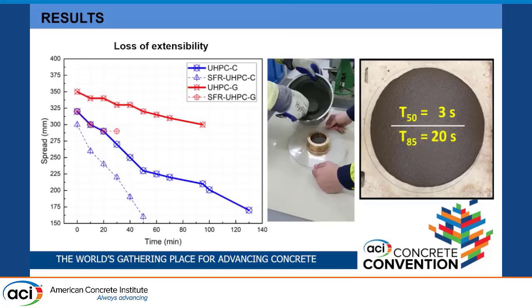Okay, and this is the graphic of the loss of the extensibility that is important for practical and industrial applications. And what we can see in the top, the red graphic is the one for the green concrete. So we can see that the blue ones that were made with the cement, the reference ones, lost the extensibility in a shorter time. So the green concrete has given us more time to work the mixture, and that is because the vitrified clay doesn't have the same reactivity as cement, so it gives us more time to handle the concrete. But you can see only 80 minutes, so this is a good application for precast industry.